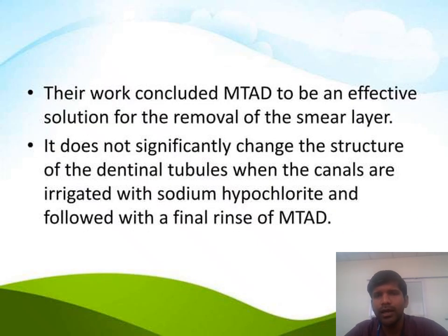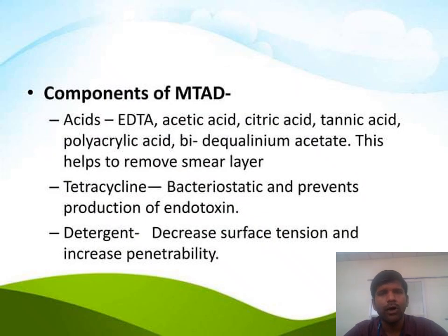Their work concluded MTAD to be an effective solution for removal of the smear layer. It does not significantly change the structure of the dentinal tubules when the canals are irrigated with sodium hypochlorite and followed with a final rinse of MTAD. Components of MTAD include acids among them EDTA, acetic acid, citric acid, tannic acid, and polyacrylic acid. Bis dequalinium acetate also helps to remove the smear layer.